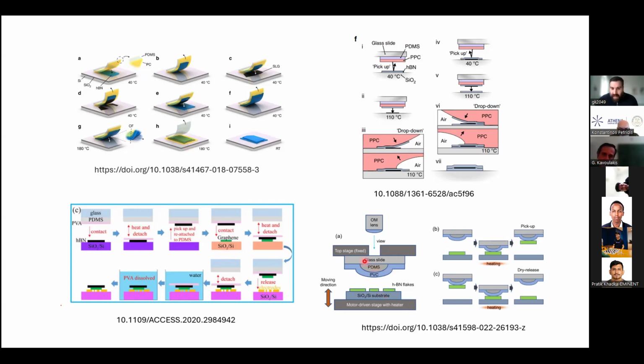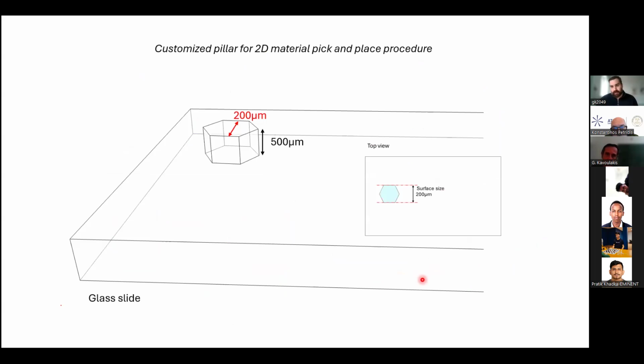They will create a dome of PDMS that will confine the contact area, and it will provide more selectivity. So there are a lot of different kinds of approaches like this one, and they confine the contact area to millimeter size. They put a high adhesion polymer film on top of the dome, and they pick and place the flakes. Motivated by that part, we designed this one.